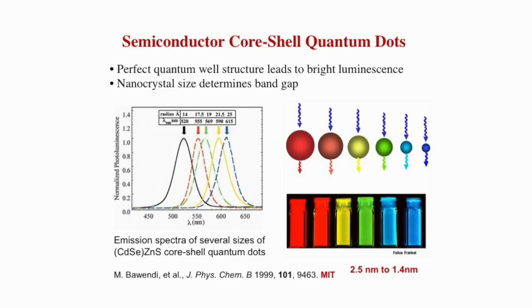And here is an example, again cadmium selenide, where by changing the size from 2.5 nanometers down to 1.4 nanometers, you can precisely change the emission wavelength from these structures, which are now currently used in TVs and displays and other things as well. So it's really precise engineering, which can be done by using the bottom-up approaches as well. So it's a matter of what your preference is, what the applications are, and which technique you want to use in order to make these nanostructures for various applications.